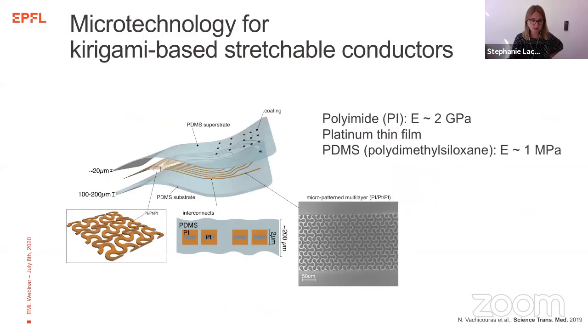And so now coming back to the neural implant, over the past year we've implemented this technology to form a fully deformable and fully compliant electrode array based on platinum. The technology I had shown you before with the microcracked gold is a spontaneous structure. The gold microcracked pattern occurs spontaneously on the gold film, but we haven't found ways to do this in other metals. With this approach, where we engineer the actual positioning of these microstructures, we can now open this up to a wide range of materials, in particular platinum, which is one of the few materials that you can routinely implement into clinical implantable devices.